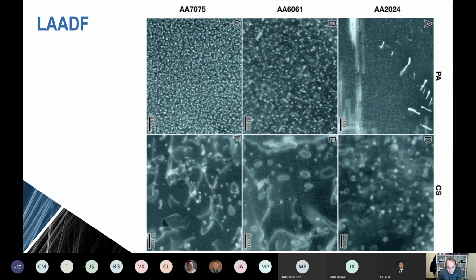We see some dislocations, but it's not a huge dislocation density, and that's quite important for us. The second thing is you can see, well, these dislocations, even the loops, will give a forest contribution to the strength. But the spacing of these sorts of obstacles is at least an order of magnitude or 2 larger than the spacing of the precipitates that appear in the normally thermally treated materials. And so these dislocation debris cannot be the full story of what controls the strength of these materials.